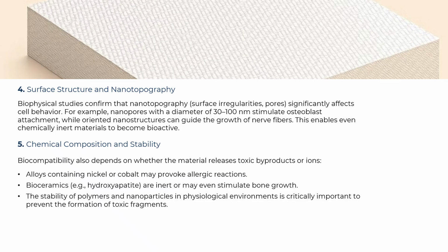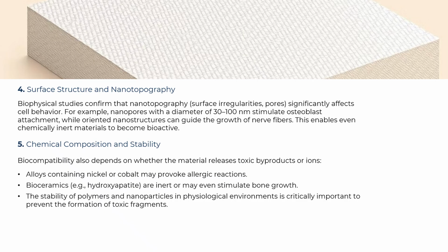Structure and nano-relief on the surface. Biophysical studies confirm that nanorelief, surface irregularities and pores, significantly affect cell behavior. For example, nanopores with a diameter of 30-100 nanometers stimulate the attachment of osteoblasts, and oriented nanostructures can direct the growth of nerve fibers. This allows even chemically inert materials to become bioactive.